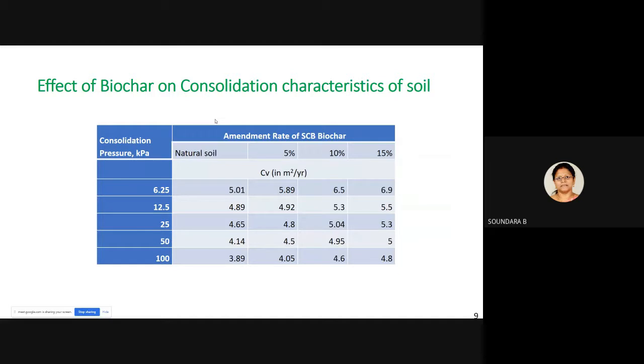Similarly, we have conducted the consolidation characteristics in order to get the settlement analysis of the biochar mixed soil. This is the Cv value, the coefficient of consolidation, which is a very important parameter in analyzing the rate of consolidation of the soil. By increasing the consolidation pressure, the Cv value normally gets decreased, but upon increasing the percentage of biochar, the Cv value gets increased. This shows that upon increasing the biochar content, the rate of consolidation could be higher in progress.